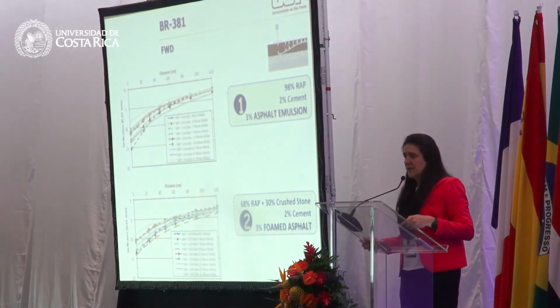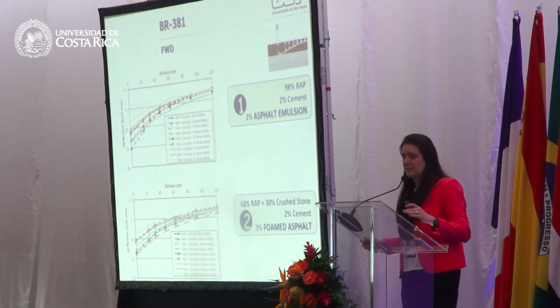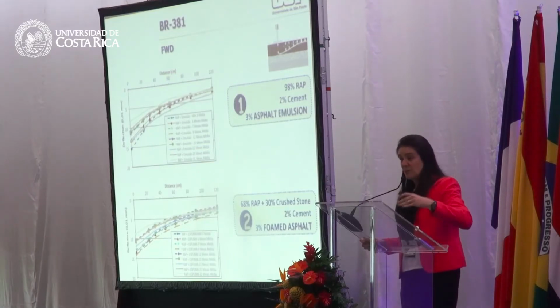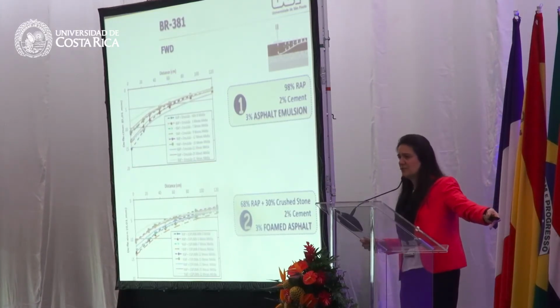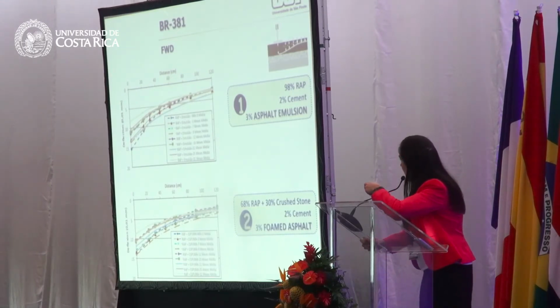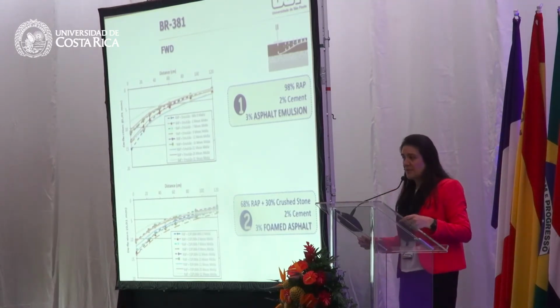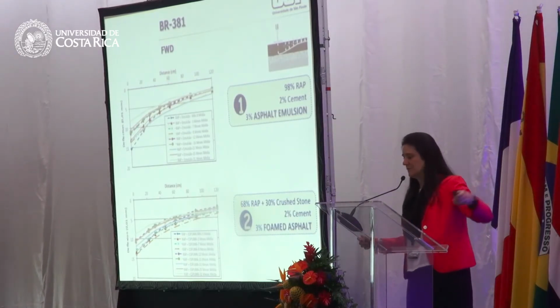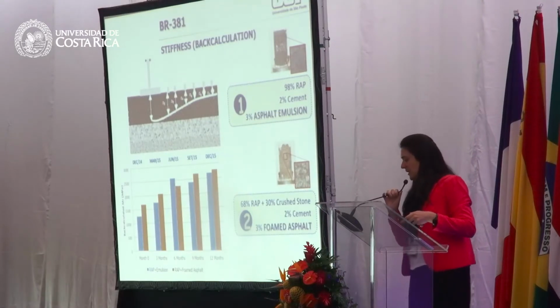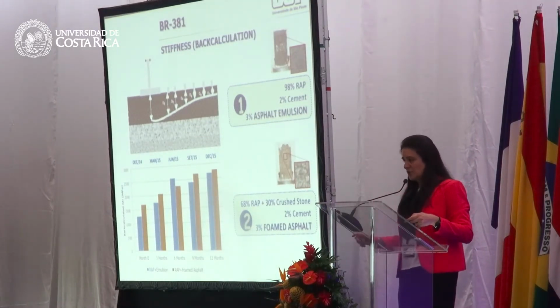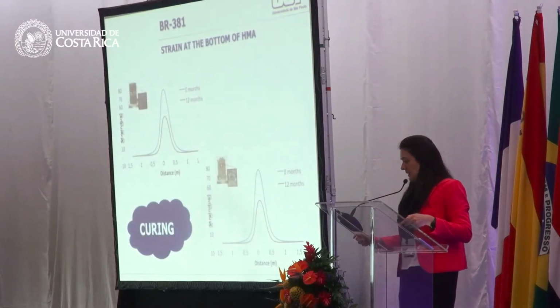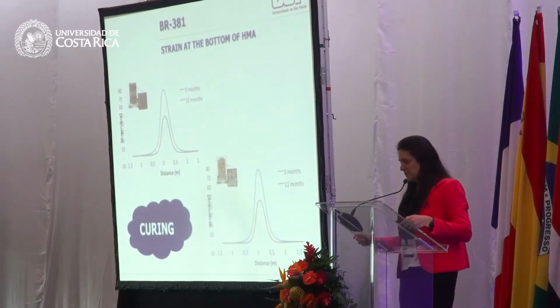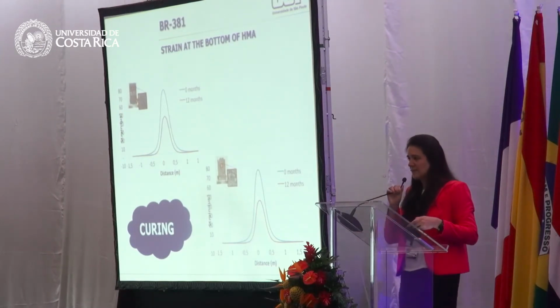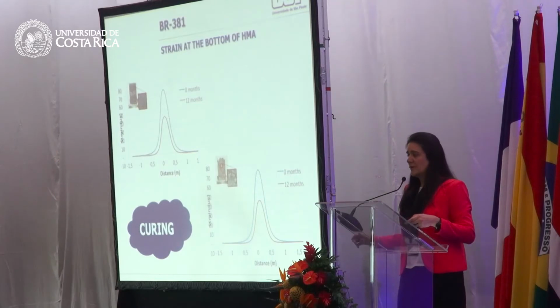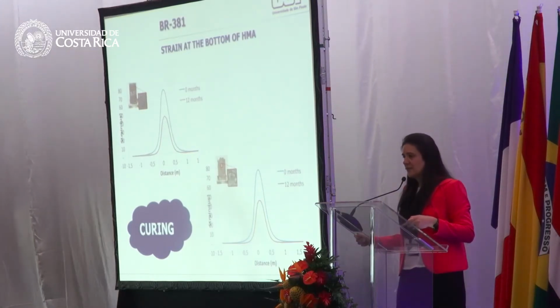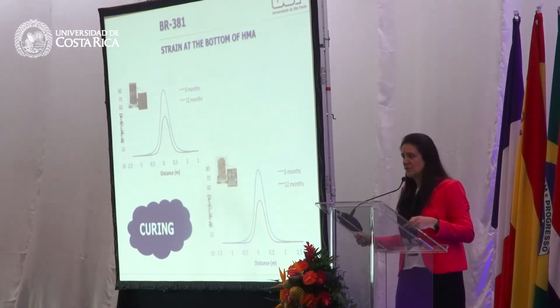Here are the deflections, and the deflections were low since the beginning. It decreased a little bit, but it was already low, not that high as the previous structure. Why? Because in this one, I have 12 centimeters of HMA instead of only 3, as I had in the other one. Some back calculations, so we can see this increase in the modulus of the base layer. The curing process, it really happens. If you check the strain that is going on the bottom of your HMA layer, you see clearly that it will decrease with time, just because of the curing process.